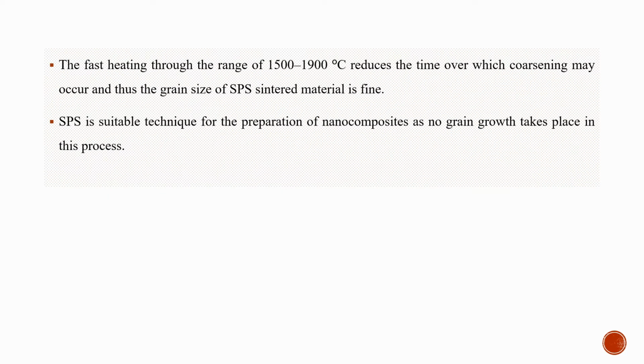The fast heating through the range of 1500 until 1900 degrees Celsius reduces the time over which coarsening may occur, and thus the grain size of SPS sintered material is fine. SPS is a suitable technique for the preparation of nanocomposites as no grain growth takes place in this process.